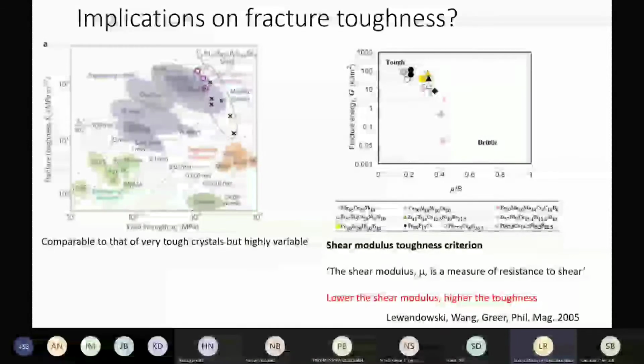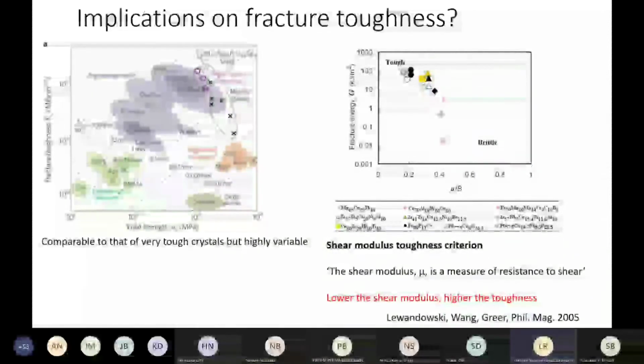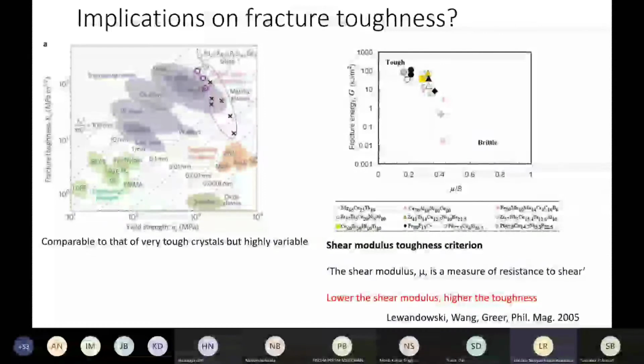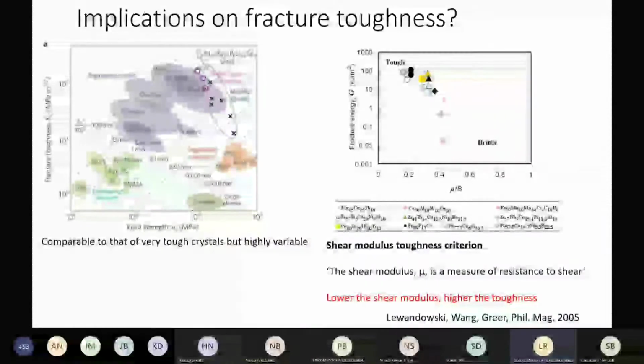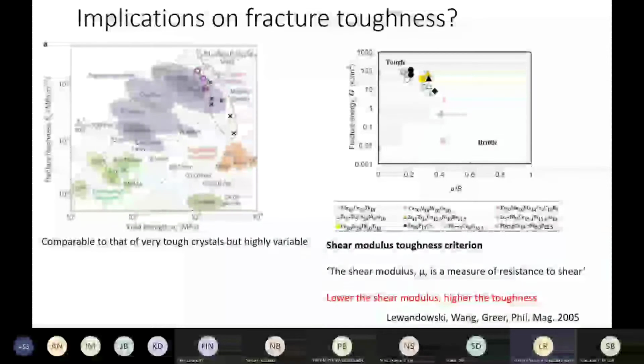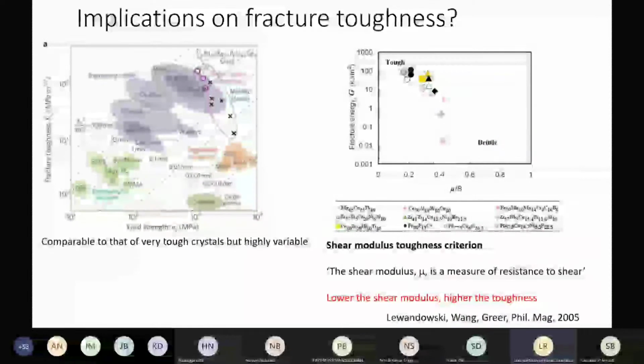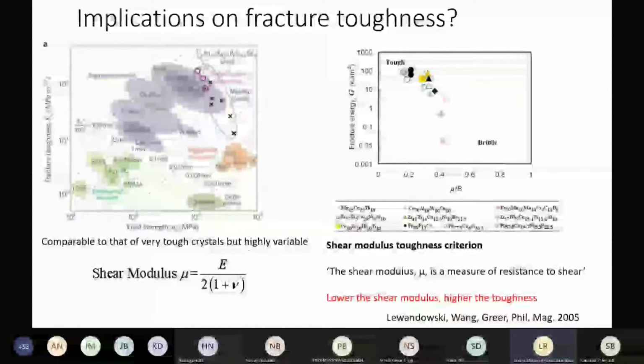So to this, they came up with a criterion. This was by Lewandowski and Greer, who worked with Wei Hua Wang, and they came up with this criterion that below a certain shear to bulk modulus ratio, you will have tough metallic glasses. And the logic was that since shear modulus is the measure of resistance to shear, if you have a lower shear modulus, the material is able to deform plastically at lower stresses. And the logic implied that if your shear is easier, then the material will undergo plastic deformation instead of failing in a brittle fashion, and hence your plasticity is higher and also toughness is going to be higher. And it certainly worked for some materials.